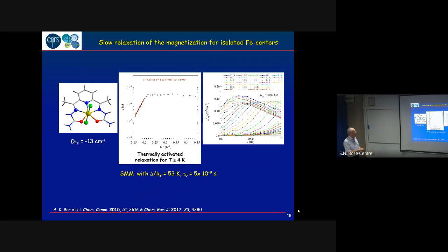And you see that the maxima of the curve comes to lower frequency as the temperature is decreased. Because it's difficult to see here, but if you go from here to here, actually we reduce the temperature. And what this means is the maxima actually is a flipping rate. And since the frequency of the maxima decreases, it means that the flipping becomes slow. So we have this slow relaxation of the magnetization, at least till a given temperature, and then the maxima stays at the same frequency. And from such kind of data, we can extract relaxation time.